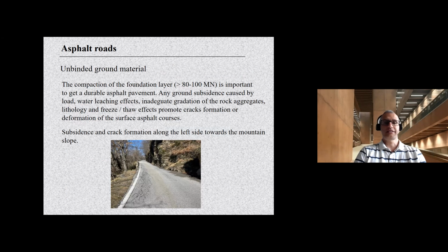As I said, the materials must be considered as a construction system, and also the unbound ground material, so the compaction of the materials plays a significant role in getting a durable asphalt pavement. And so ground subsidence, this is actually a clear case of a mountain street that goes up. You can see that there are many factors affecting the formation of cracking along the left side of the street. So freeze-thaw attacks, leaching of unbound material on the left side of the street. On the slope, this is leached away, and the street tends to crack because the support of the unbound material is no longer present.